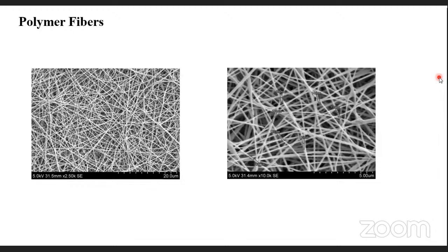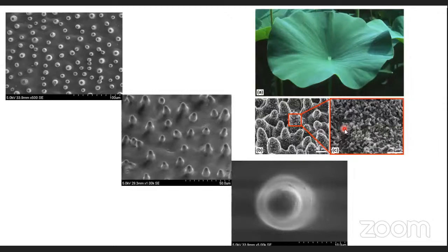Polymer fibers can also be analyzed with the electron microscope. These are beautiful images of electrospun polymer fibers. At 2,500x magnification you get an overview, and at 10,000x you can see how small the fibers are — around 100–150 nanometers in diameter. The hydrophobicity of the lotus leaf is also very interesting: due to its nanostructure alone, without any wax, it acts as a hydrophobic surface. SEM reveals this complex nanostructure clearly.